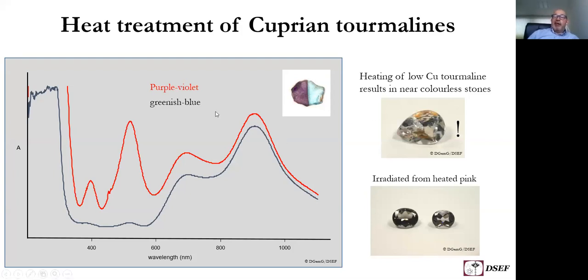So you have to be very careful, and you have actually to analyze the absorption spectrum first before you heat treat the stone, which we do for the trade. You can restore some of the color by irradiation, because by irradiation you can again oxidize the manganese, but then it results more in a purple, pale purple amethyst type color, which is not very attractive.